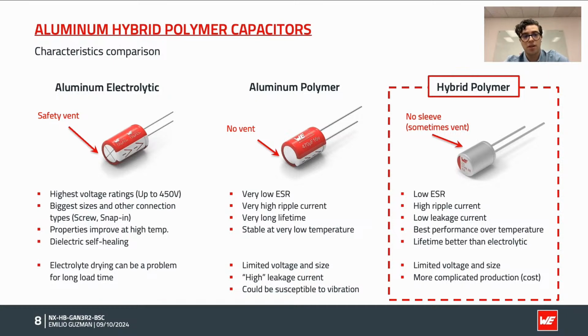Although some disadvantages can be that the electrolyte drying can be a problem for long load times. For the aluminum polymer, in contrast, it has very low ESR, it has very high ripple current capability, has a very long lifetime, and it's very stable at low temperatures. Although for the disadvantages, it is limited in voltage and size, it has a somewhat high leakage current, and it could be susceptible to vibration.